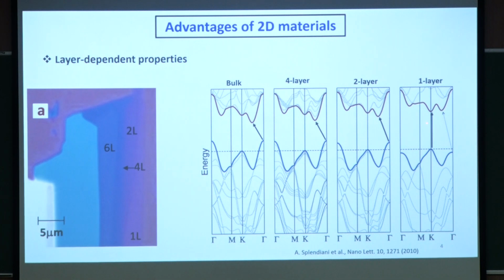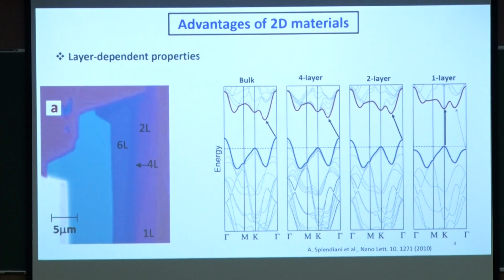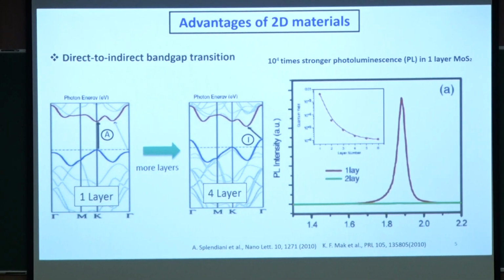But once you go to the monolayer limit, then you have this direct band gap, which is the smallest band gap now. So this monolayer of MoS2 behaves as a direct band gap material. And what are the consequences? There's a huge amount of consequence.